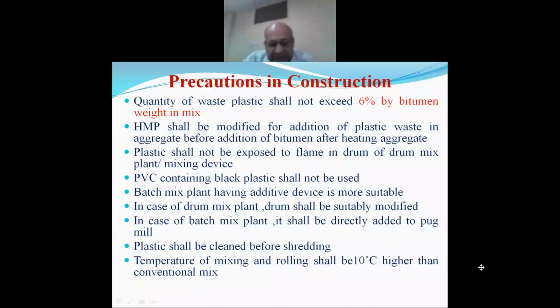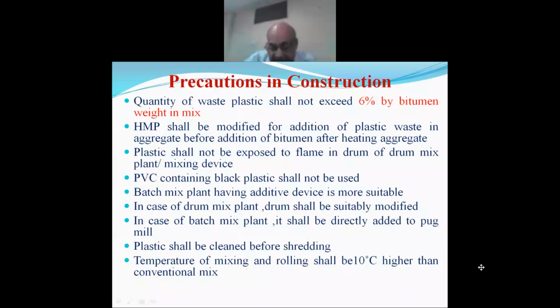The hot mix plant to be used in the modification of the plastic, I will tell you later on. Plastic shall not be exposed to the flame. It will be modified in such a way that there should not be any contact between the flame and plastic or plastic coated aggregate.